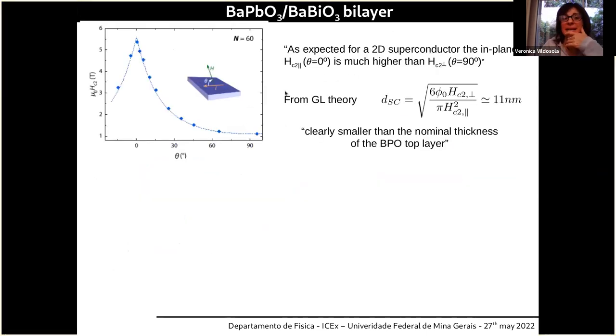They claim that this superconductivity was two-dimensional. They performed measurements applying a magnetic field, varying the angle of the magnetic field, and they observed that the behavior was that of a two-dimensional superconductor: the critical field at zero degrees was much higher than the one that was perpendicular.